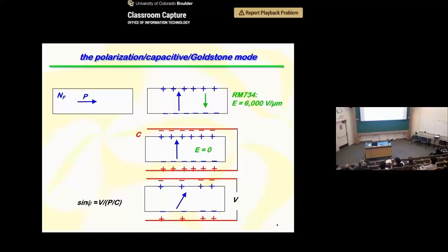free charge and polarization charge in the same plane. So if you have, say, a gold electrode and you just put the ferroelectric nematic in contact with the electrode, then you still end up with a nanometer thick layer that's insulating. So you end up with a surface capacitance. So if you tilt over the polarization, you will have some electric field in the capacitors, and that will cost you a little bit of energy, but nothing like in the bare case.